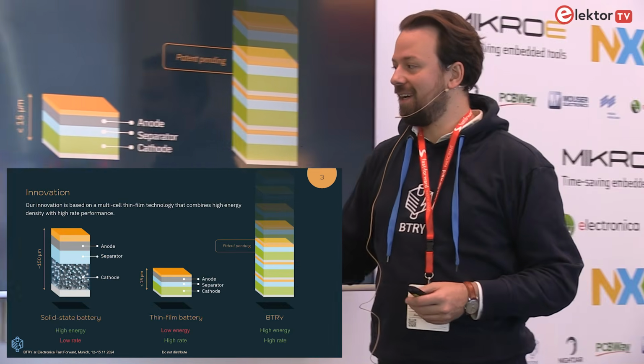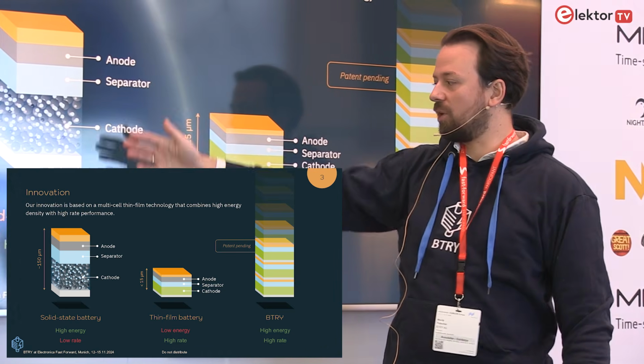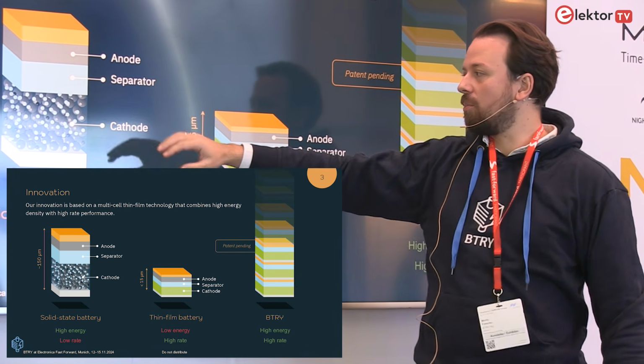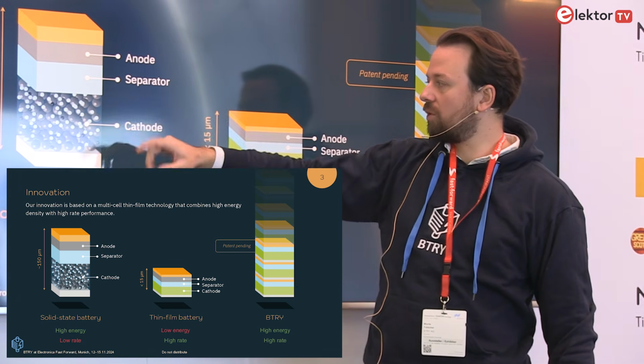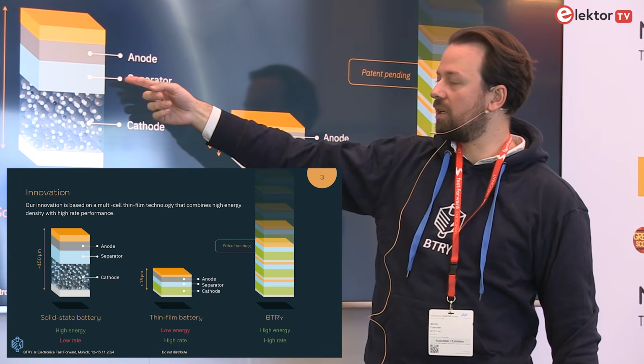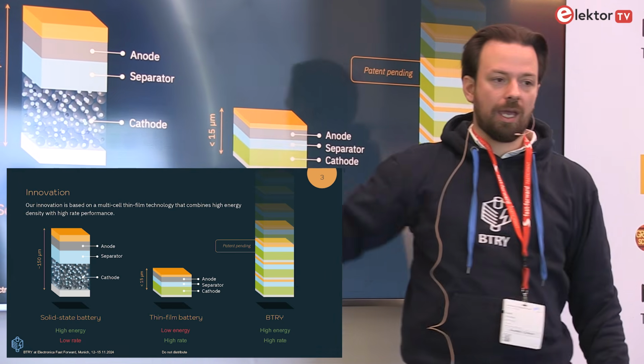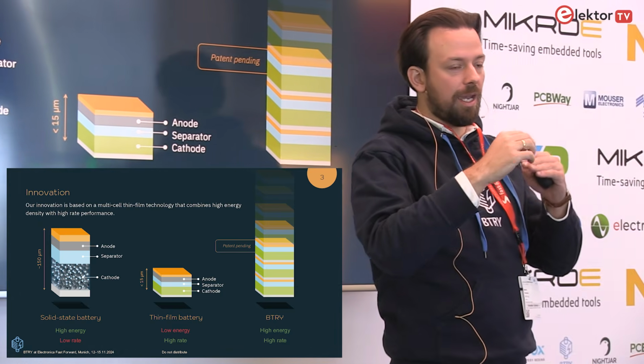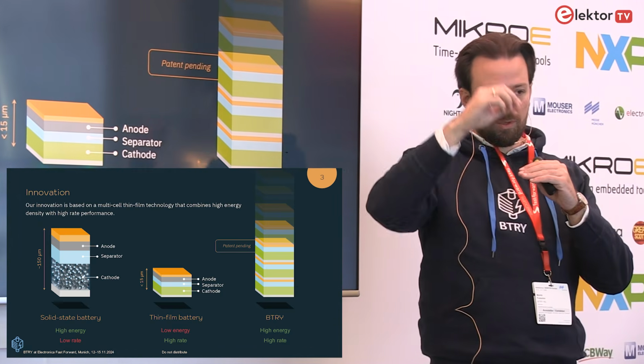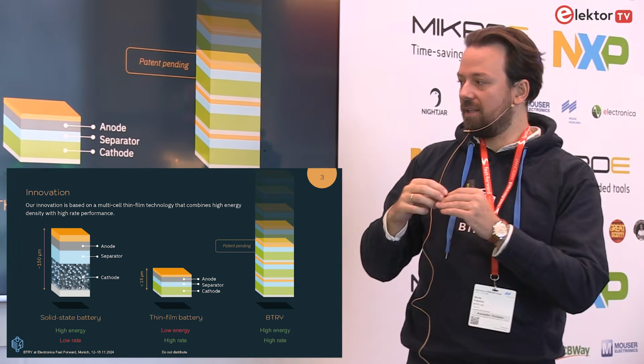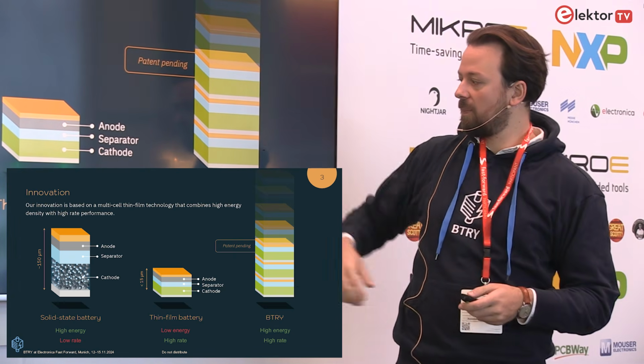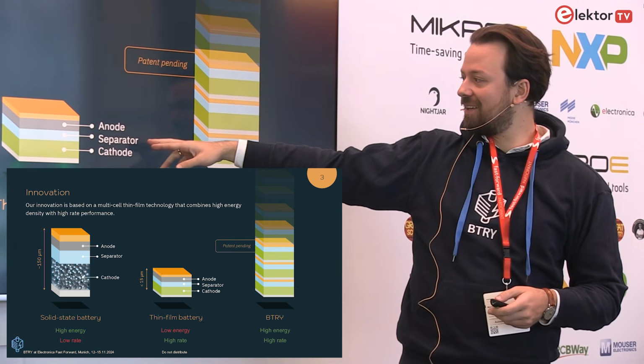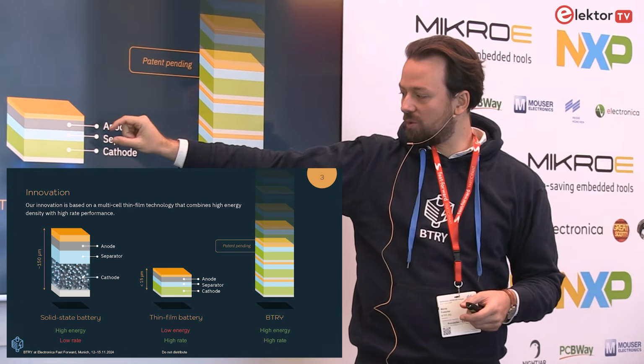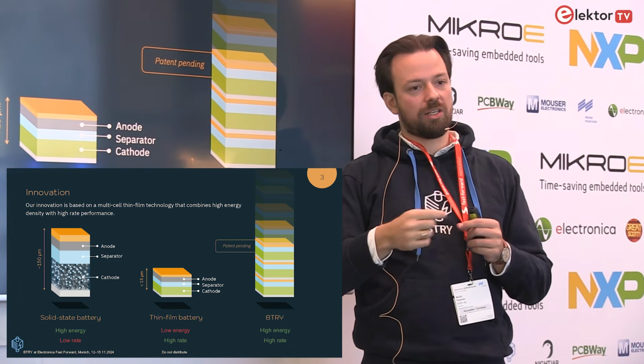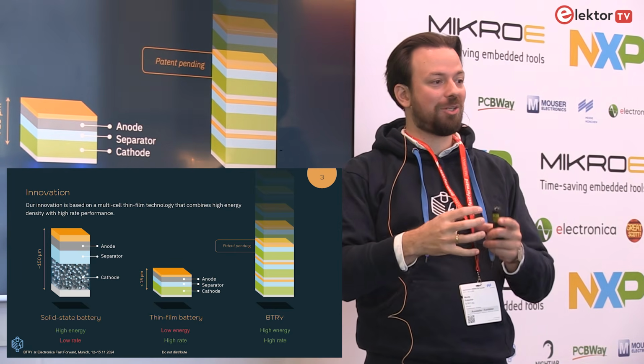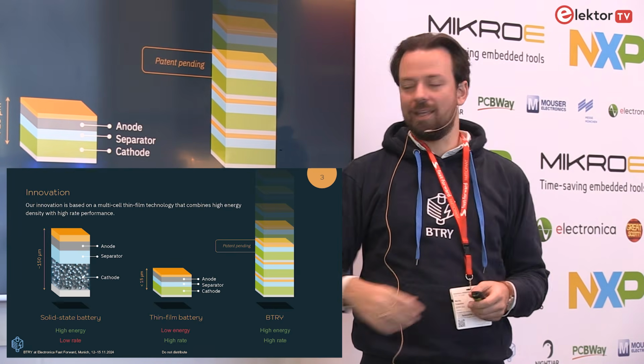How do we do it? Here you can see what a typical solid-state battery looks like. You usually have thick electrodes, such as a cathode and an anode, with a separator. And because the electrodes are thick, it takes time for the ions and electrons to travel through the whole cathode. And this time limits the rate performance. Thin batteries, on the other hand, are very thin, and so we can have very high charging and discharging rates, but since you do not have a lot of energy per area, the energy is low.